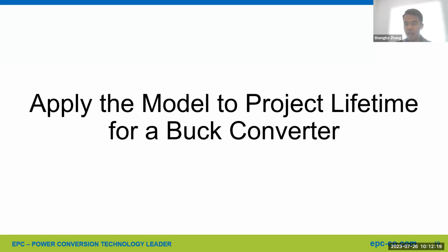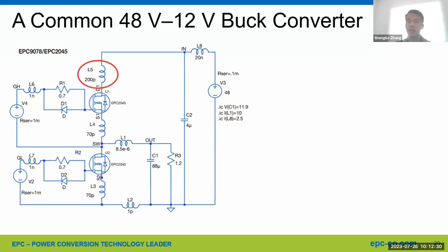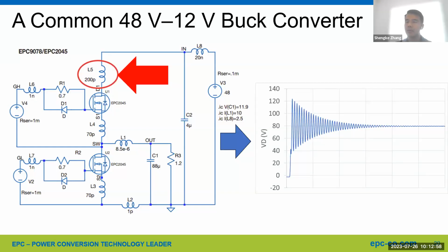So after we have a model, now let's apply the model we developed to project lifetime for a buck converter as an example. Here is a common 48 volt to 12 volt buck converter operating in continuous conduction mode. All parasitic inductances were added in the schematics. Now we introduce 200 picohenry L5 parasitic inductance to simulate a worst case scenario in application. So in SPICE modeling, we observe a peak voltage ring of approximately 120 volt with bus voltage at 80 volt during turnoff. So this waveform is potentially the worst case scenario in real world application.